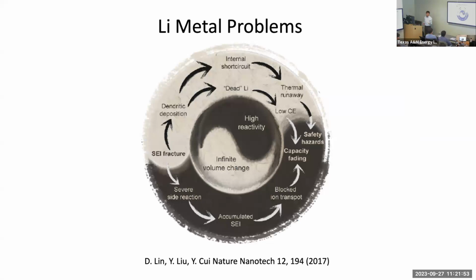One is during plating and stripping, this volume fluctuation is too big. The second is metallic lithium is so reactive chemically with nearly everything, right? So these two things adding together make it so hard to handle. So in 2017, we published this Nature Nanotech perspective article. This is very highly cited, probably close to 4,000, 5,000 citations right now. And to really show the whole world how we solve the problem, we need to address the root causes.